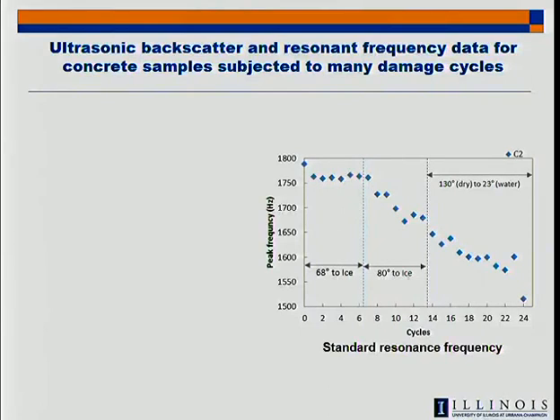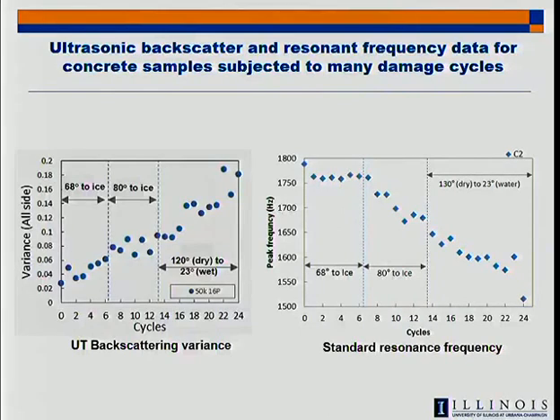We ran the test on that same sample, and here we see our backscatter coefficient is going up, kind of mirroring the same process. And this is a method that can be applied to anything in the field in a non-contact way. So I just show this to show that we have come up with a scheme that's able to characterize these very small microcracks. Hopefully we're working on quantifying this, putting some meaning behind that number so that we can go back and compute the cracking.